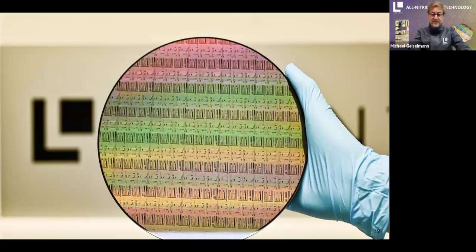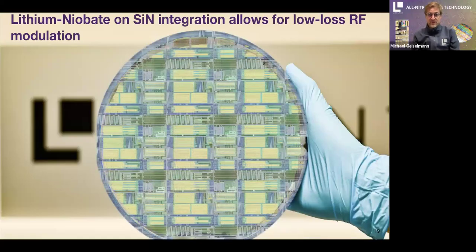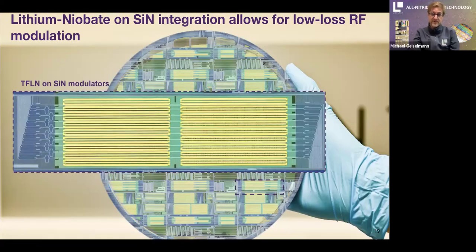So again, we start from a 200 millimeter wafer that is fabricated in a 200 millimeter CMOS line, and then we integrate for very low loss RF modulation. We integrate that with lithium niobate. And here is a final chip, where on the left hand side you see the passive components which are made of nitride. So you see splitters and the waveguides in nitride in the blue region. And then you go to the active region, which is the lithium niobate, shown here in green, and the yellow part, this is the electrodes where we modulate these push-pull